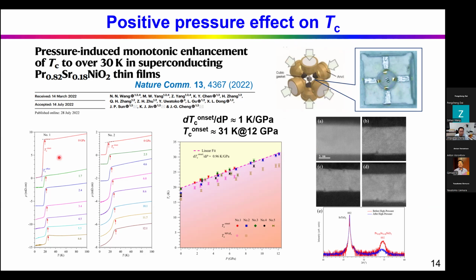Finally, we successfully observed the superconducting transition under different pressures. We found that the transition temperature increases with pressure almost linearly with a slope of 1 Kelvin per gigapascal, and we measured up to 12 GPa. The highest Tc can reach about 30 Kelvin. But as you can see here, below 4 to 5 GPa, we can still reach zero resistivity, while at high pressures we can only observe a drop of resistivity, but cannot reach zero resistivity.